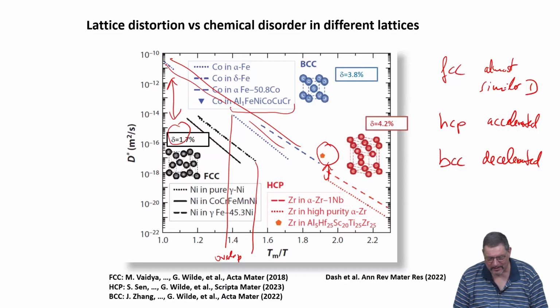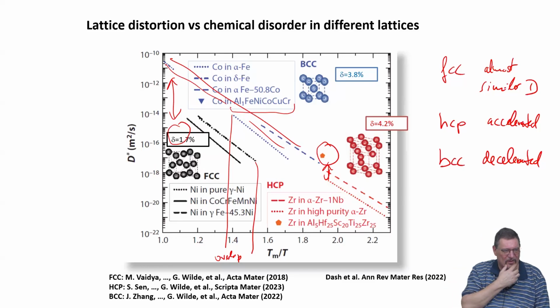If you look at it in terms of lattice distortions, certainly for the FCC, these are smallest. This is maybe why the diffusion is rather unaffected by going from rather pure to very concentrated solutions. BCC, HCP both have something like more than 3%, but maybe this limit of 3%, which was suggested in literature, is not wrong. Maybe it's more like between, but 3.8 and 4.2 is not such a big difference, right? And one goes down and one goes up. So again, there's a little doubt whether this can be put into a very general statement that a certain limited number of lattice distortion would give you either a deceleration or an acceleration of the diffusivity. I kind of doubt it a little bit.